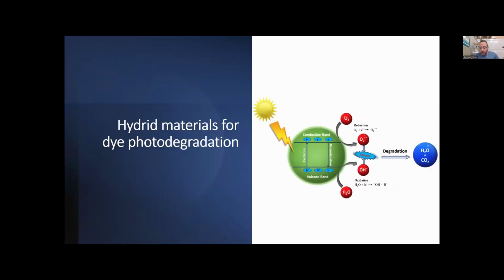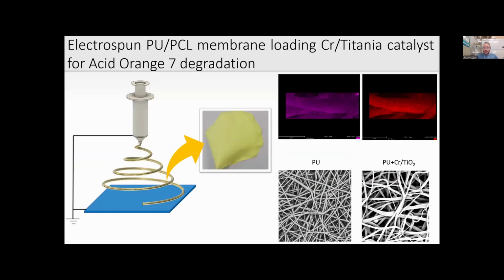The last approach concerned the use of hybrid material for dye photodegradation. In this case, we applied an electrospinning process again just to design a novel kind of polyurethane polycaprolactone membrane doped with a chromium-doped titania catalyst produced through a sol-gel sustainable process to photodegrade acid orange 7.